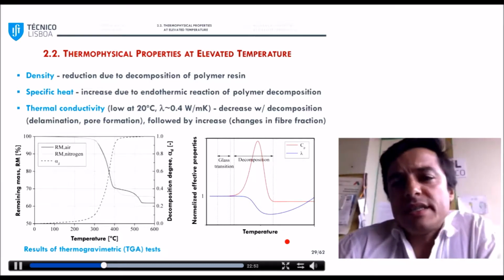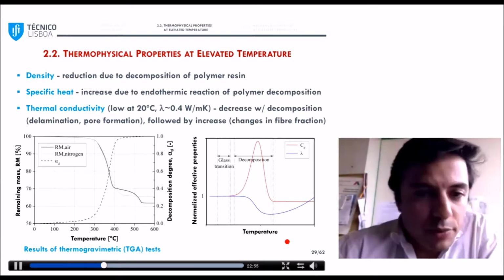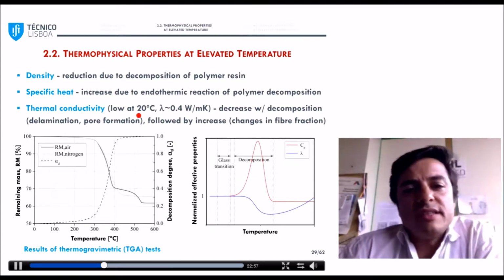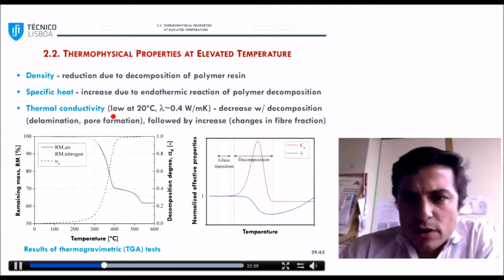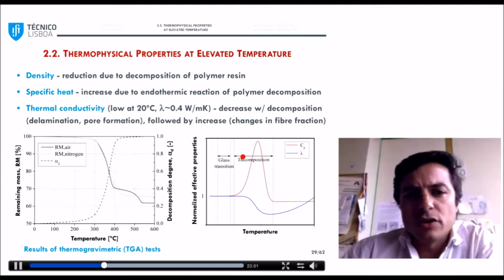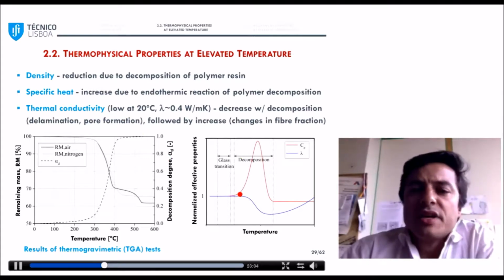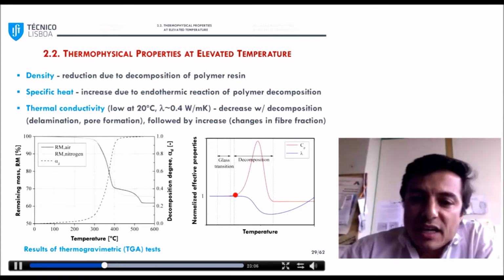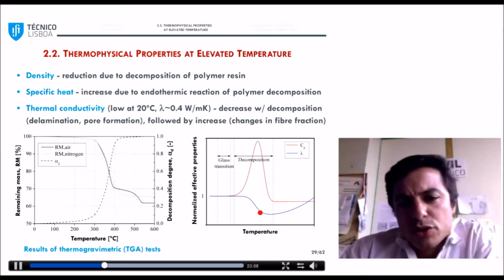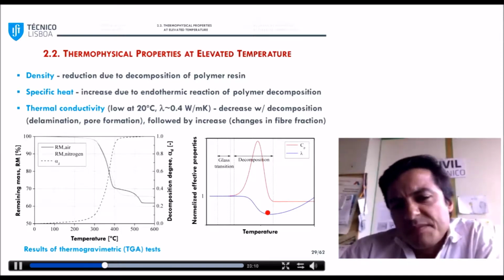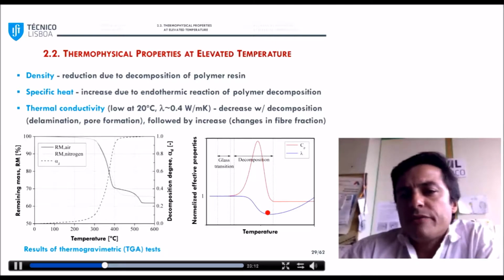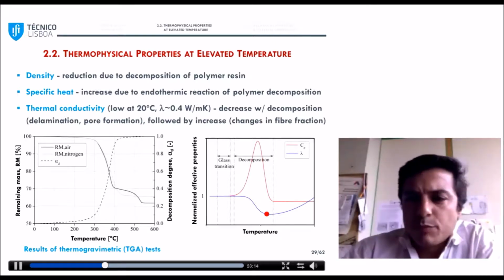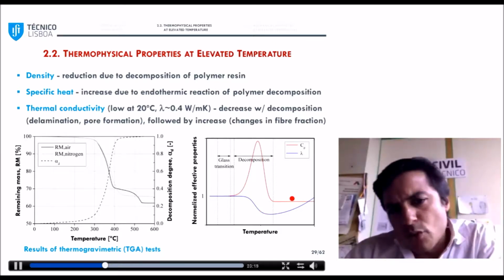So for thermal conductivity, you can see actually this was the property I was mentioning that is very low. This is the one that reflects thermal insulation capacity, not the specific heat. So you can see that it initially presents a reduction here with the decomposition of the matrix. This is basically due to the fact that you have delamination and pore formation in the material, and this helps insulating.